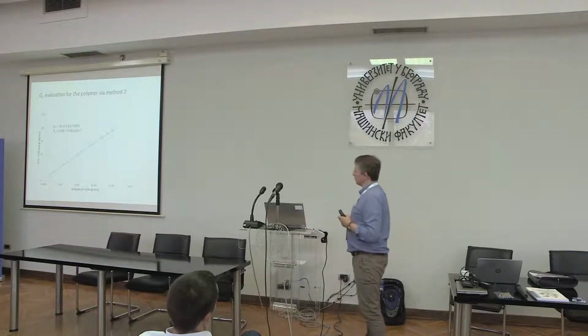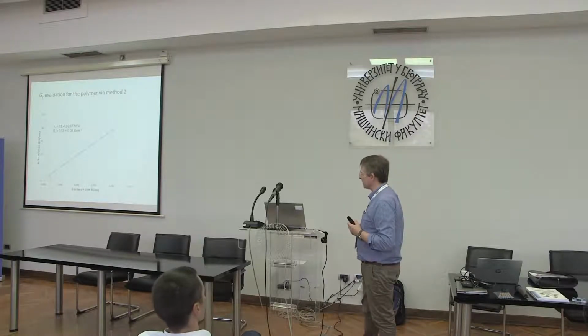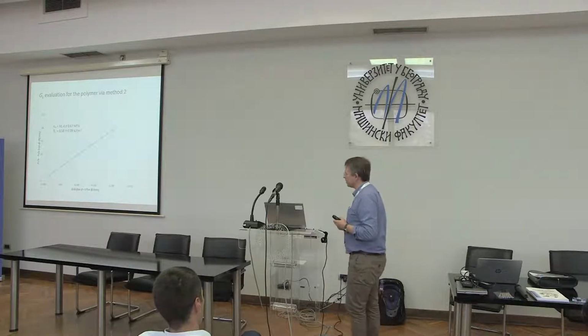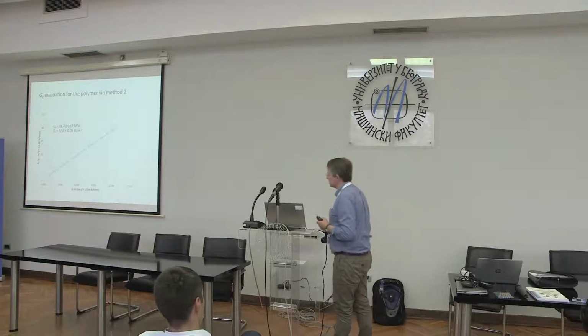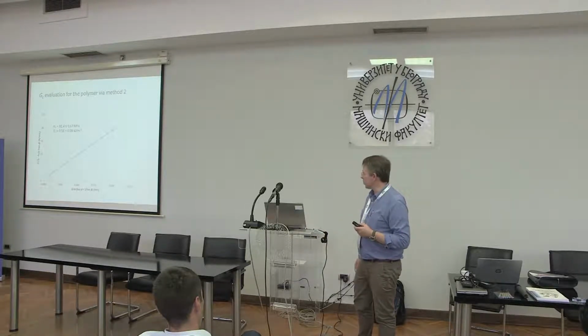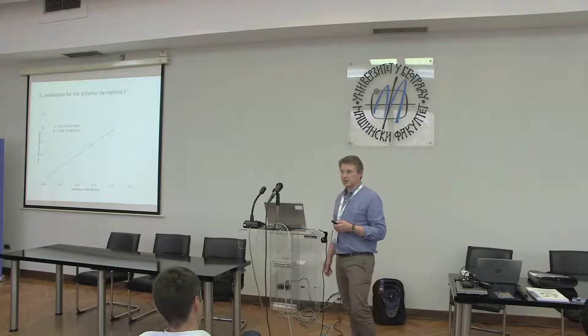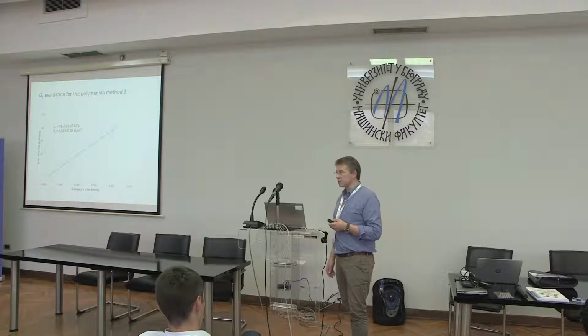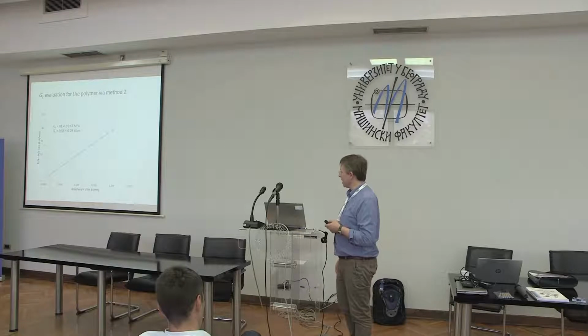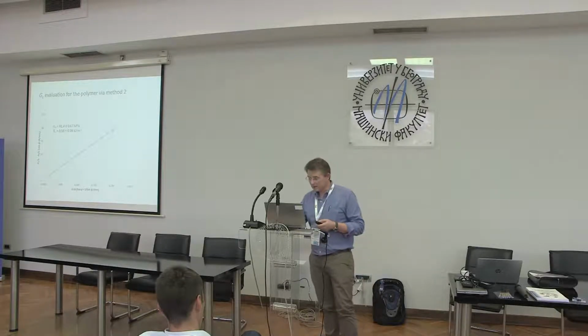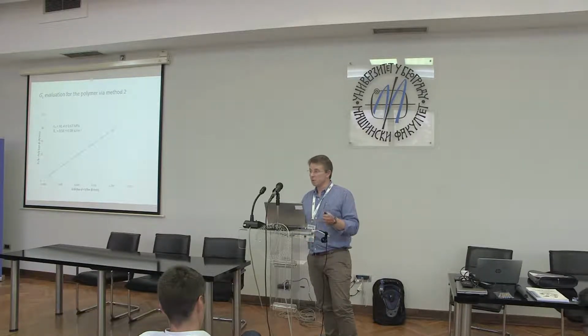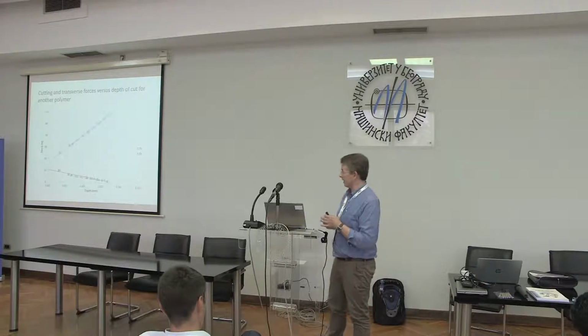So for this particular polymer, we're measuring about 0.6 kilojoule per meter squared for the energy release rate, and we measured in this case 91 megapascal for the yield stress. That's relatively high. We know that was around a factor of 2 on yield stress, so there's a lot of work hardening, strain hardening taking place in this. We tended to find the values were quite comparable to the values that we got with LEFM, when using materials that we could validate via LEFM.